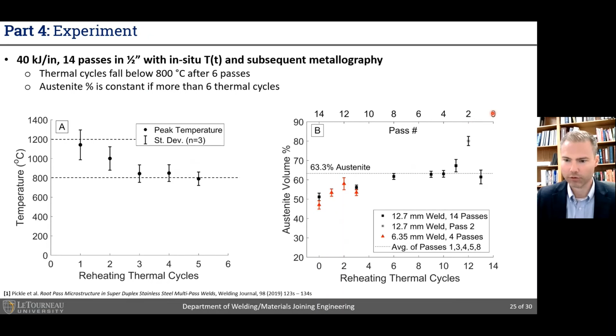So increasing the number of passes, we're just going up through the position of the weld, and notably, with the exception of this outlier, which had dramatically different microstructure, and we consider it non-representative, not exactly sure why, but not a representative data point. The key point is that as we move up from 0 to pass 8, all of these have a minimum of 6 reheating thermal cycles. The austenite volume fraction is effectively constant.